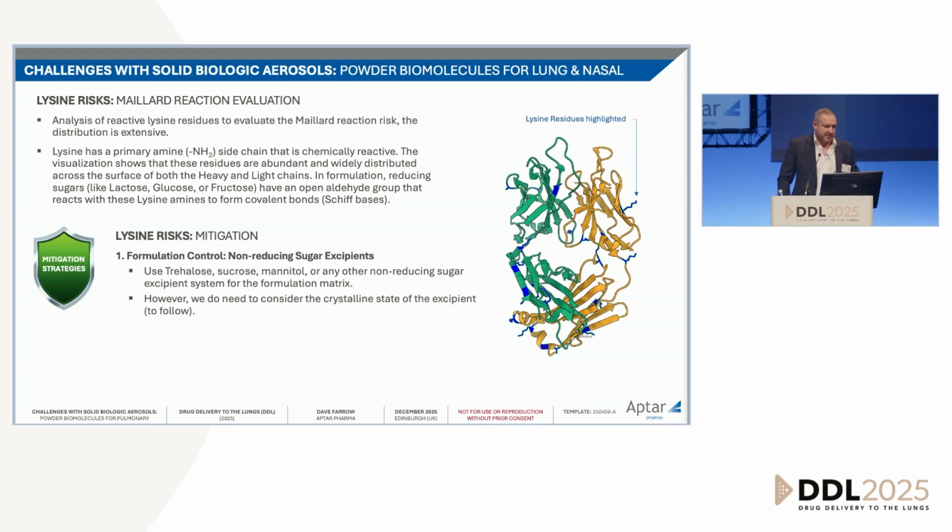Maillard reaction is pretty easy. Here, obviously, we've highlighted the lysine residues. They're everywhere, as you'd expect, and they're extending into the solvent interface. So, again, no reducing sugars, no lactose, glucose, or fructose. Yes, to trehalose, sucrose, and mannitol. And again, most of us know that, but it really kind of backs up the science behind it. But it's not just about what's chemically related. We need to think about the structure of the matrix as well, and we'll talk about that shortly.